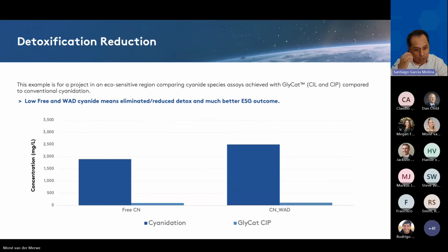As mentioned before, one of the most significant benefits of glycat technology is the downstream reduction of cyanide compounds formation. Because starving cyanide conditions are typical in the glycat environment, the amount of WAD and free cyanides are significantly reduced before detoxification. In this case, the operation was in an area that was sensitive to strict environmental requirement conditions. The reduction of cyanide species before detoxification was drastic and practically eliminated the necessity of using any detoxification reagents. Also, we can see the other cyanide compounds being reduced significantly, but we are not showing that in this specific graph.